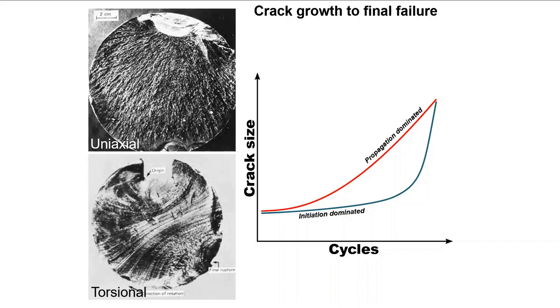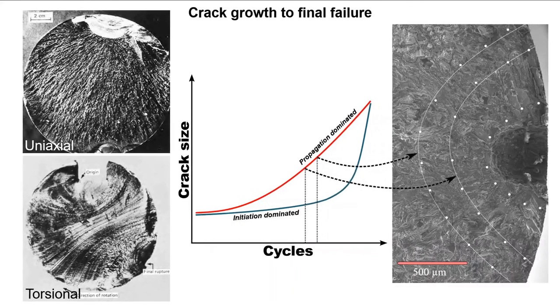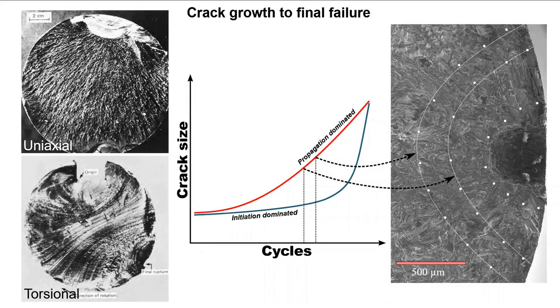Materials that exhibit this type of initiation, followed by fast fracture, are typically those which are high strength and therefore have lower ductility, or materials that have BCC and HCP crystal structures. FCC-type materials typically have propagation-dominated behavior. Here, the fracture surface of an aluminium alloy near an initiating defect is shown. The striations appearing on the fracture surface show that the crack has grown regularly and can be tabulated to assess growth rates if the number of cycles are known. This isn't the most prevalent way of assessing fatigue behavior, as it will only assess a limited amount of material.